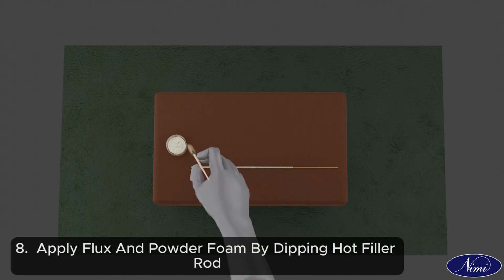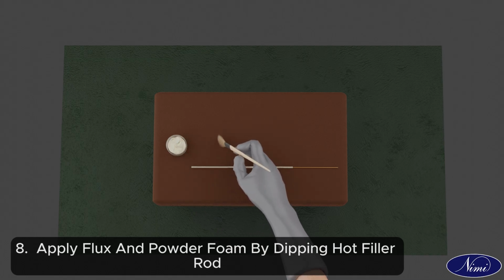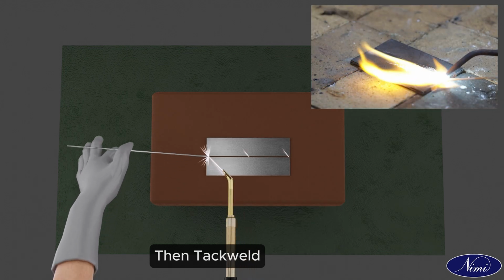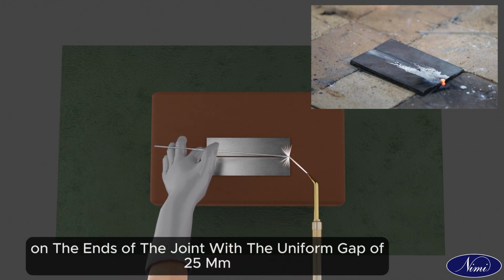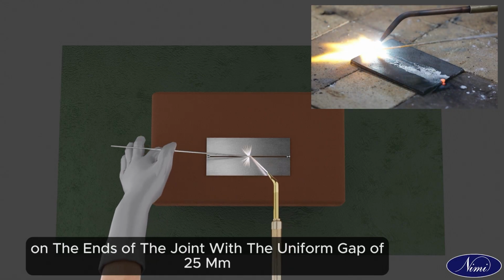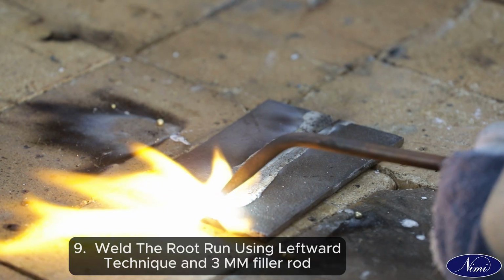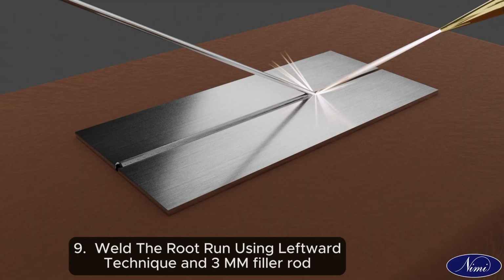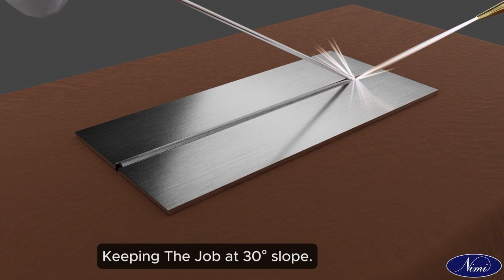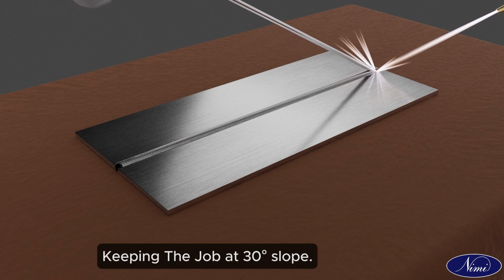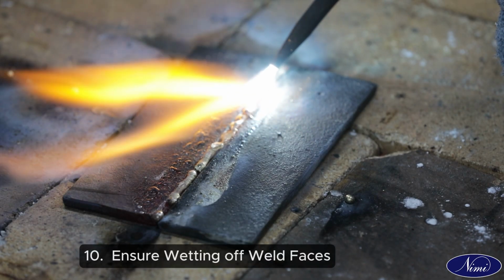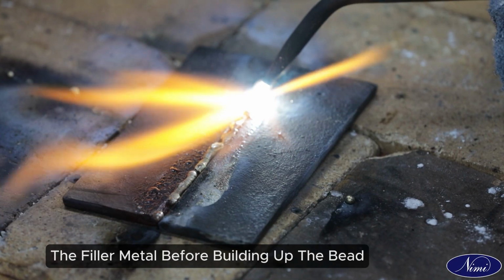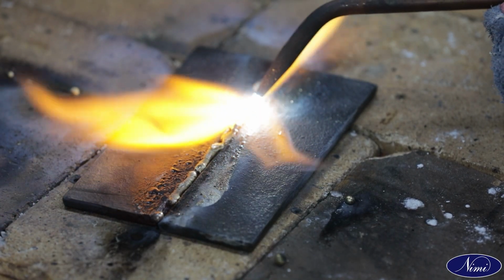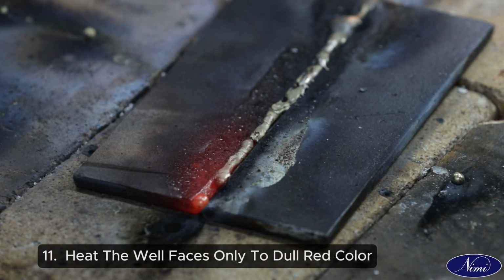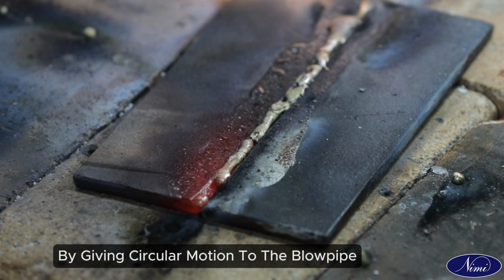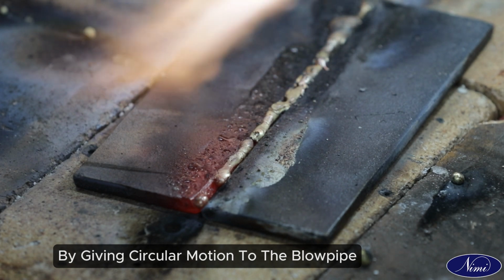8. Apply flux in powder form by dipping the hot filler rod. Then tack weld on the ends of the joint with a uniform gap of 2.5 mm. 9. Weld the root run using leftward technique and 3 mm filler rod, keeping the job at 30-degree slope. 10. Ensure wetting of weld faces by the filler metal before building up the bead. 11. Heat the weld faces only to dull red color by giving circular motion to the blowpipe.